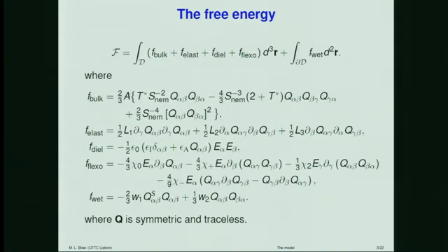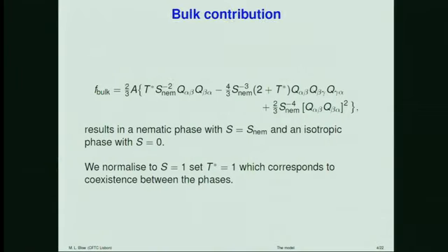So we model our nematic liquid crystal using a Landau-de Gennes free energy in the Q-tensor formalism. You've probably seen this or something like it before, but we have various contributions to the free energy, including the bulk terms, elastic terms, electric terms, and a wetting term. And the bulk contribution may be written in a variety of ways.